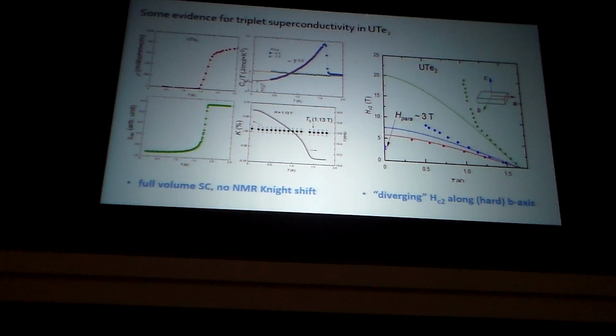So what's the evidence that this thing is a triplet superconductor? Well, of course, you can't tell from the resistivity. But what you can tell from is something called the Knight shift. The Knight shift is an NMR technique that measures the spin susceptibility of the Cooper pairs. So when you have a regular s-wave superconductor, or even parity superconductor, with spins like this, when you enter into the superconducting state, you expect the Knight shift, or the spin susceptibility, to go to 0. But you see in this work, the spin susceptibility, which is this data here, doesn't change at all when you go through the transition temperature. So this is very suggestive that you have a spin triplet type of pairing.